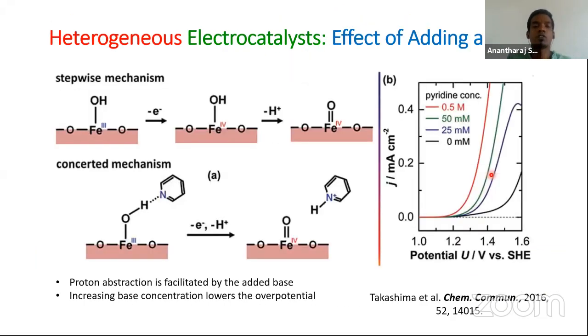And in heterogeneous electrocatalysis, often people make interesting findings, and this one is about change in mechanism just by the addition of base. So you can wonder how adding a base will change the mechanism, because most of the neutral water splitting studies are done in buffered solution. So when you add a small amount of base, the pH of the solution is not going to change. After all, that is the reason why we use buffer solution. So this work by this group of authors was published very recently.